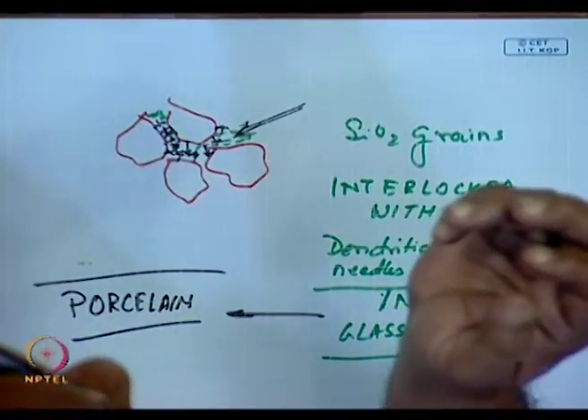The ordinary teacup which you buy for say 4 rupees or 5 rupees as opposed to a Hitkari cup, where is the fundamental difference? Barring everything, the amount of glassy phase in the Hitkari cup is much lesser than in the 5 rupee cup. As a result, the Hitkari cup does not break that easily, whereas the common 5 rupee cup, porcelain cup that you buy, or the 10 rupee one, they break very easily. This is called liquid phase sintering.